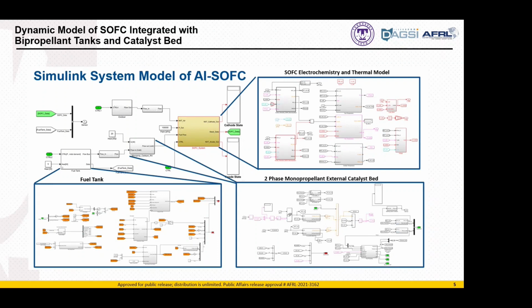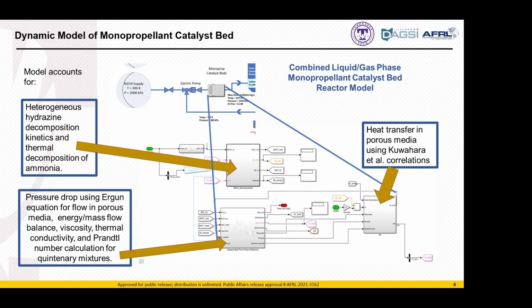But you can see all the physics that's involved to study the bipropellant tank dynamics, two-phase monopropellant catalyst bed flow, and all of the electrochemistry and the thermal balances that are involved in the SOFC. Just to highlight one component as an example, we developed a catalyst bed Simulink model that would account for heterogeneous hydrazine decomposition kinetics and the thermal decomposition of ammonia. It accounts for pressure drop in this porous media. So this is a packed iridium nickel catalyst bed that's commonly used in hydrazine monopropellant rockets right now.